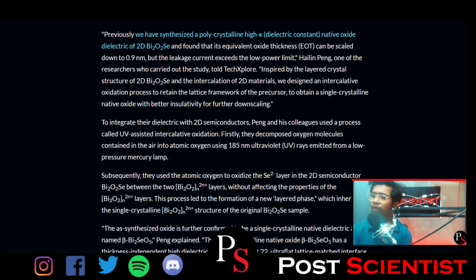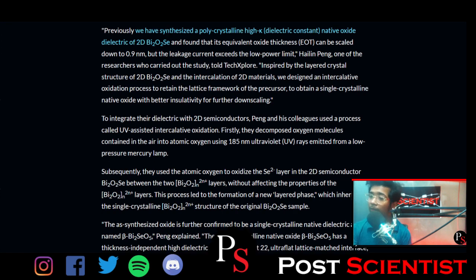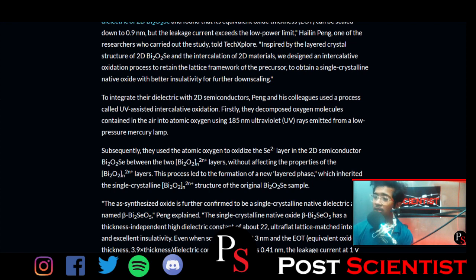Previously, we have synthesized a polycrystalline high K dielectric constant native oxide dielectric of 2D bismuth oxyselenide and found that its equivalent oxide thickness, EOT, can be scaled down to 0.9 nanometer, but the leakage current exceeds the low power limit, Hailin Peng, one of the researchers who carried out the study, told Tech Xplore.